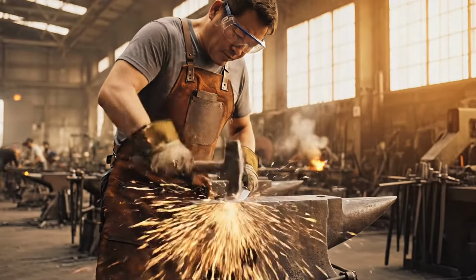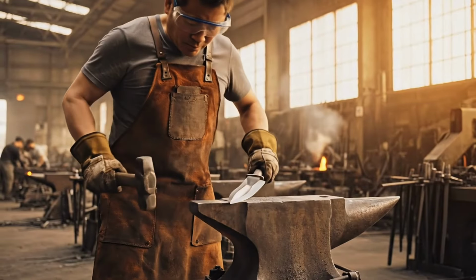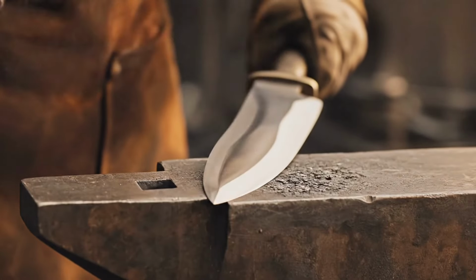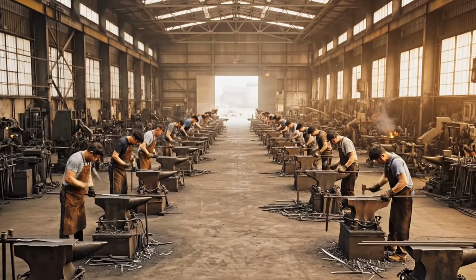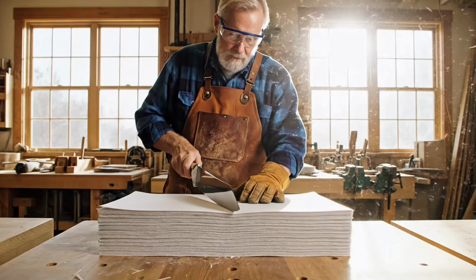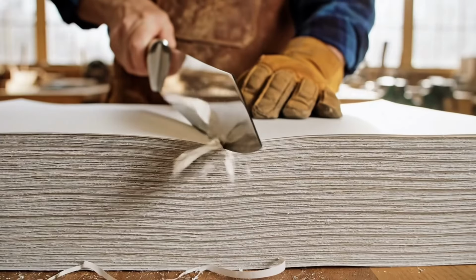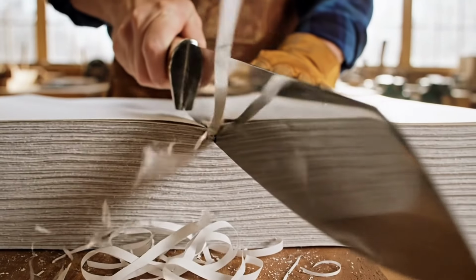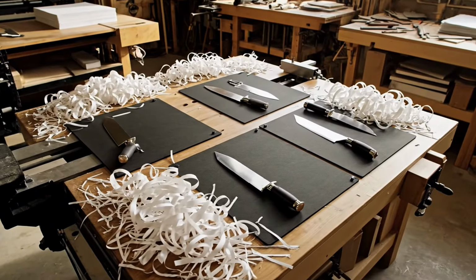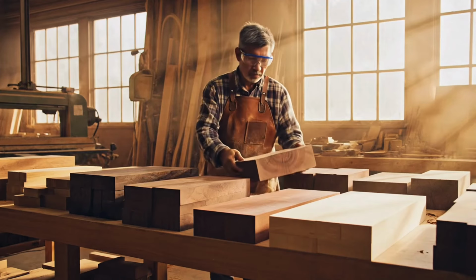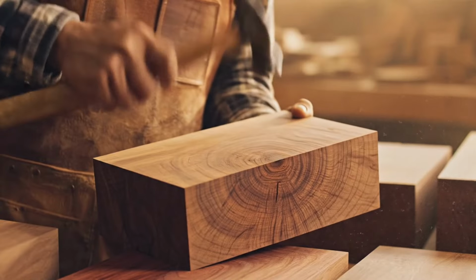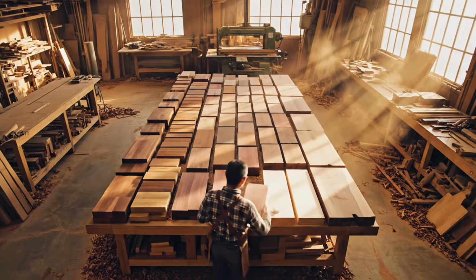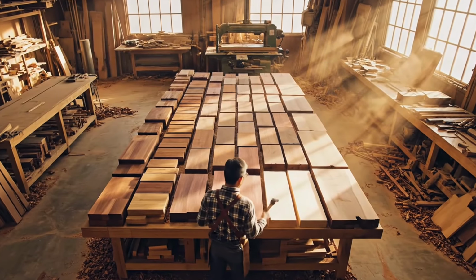To test overall toughness, the blade is tapped against a steel rod, ensuring the edge survives controlled impact without chipping. A final sharpness test slices through layered paper to confirm the blade performs consistently after stress testing. Handle crafting begins with selecting hardwood blocks, each chosen for density, grain stability, and long-term durability.